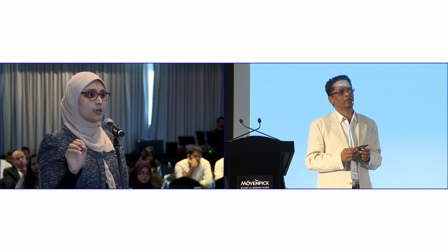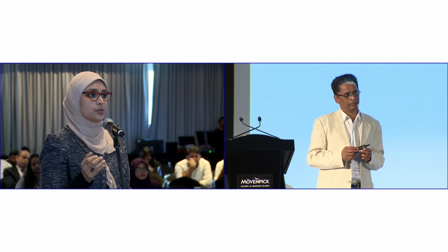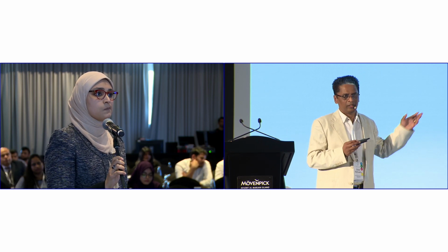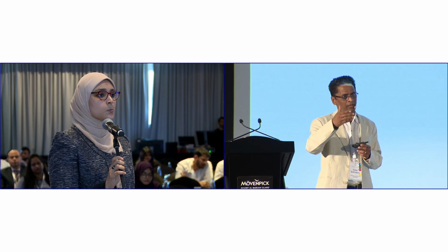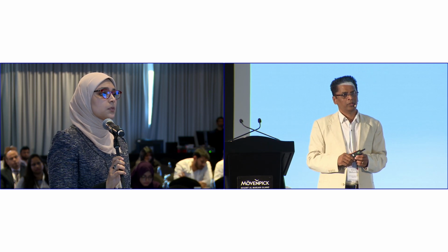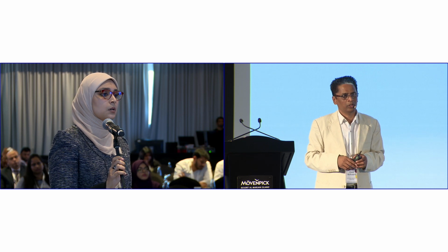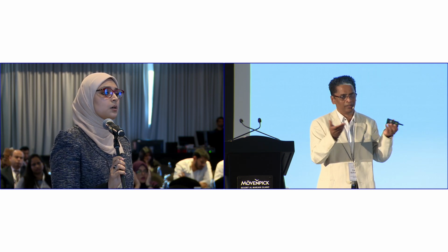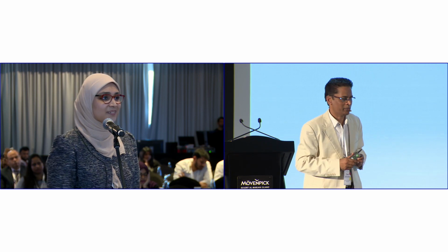No. Are the post-stability measurements done after a mild process or a harsh process? Because to my knowledge, it should suffer from some sort of oxidation. Yes, that's what happens: it goes to iron oxide, hydroxides on the surface. The phosphide won't be stable all the time. If you allow for a longer time, you will see the surface getting more and more oxidized. If you allow for more than 200 hours or so, you may even have more phosphate. Okay, thank you. That's the one problem with the phosphide.